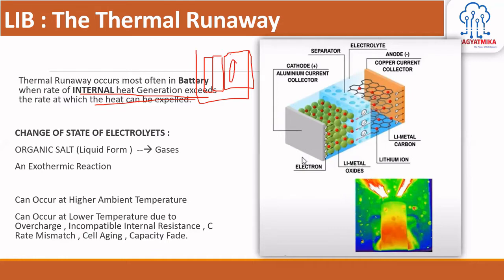And if this temperature is not managed, the rate of generation of this temperature exceeds the rate at which it is getting expelled. This can lead to a further rise in temperature, and a thermal runaway stage starts. The state of your electrolytes changes from the liquid form to the gaseous form, and the exothermic reaction starts. Generally, it can occur at higher ambient temperatures, like your external temperature.